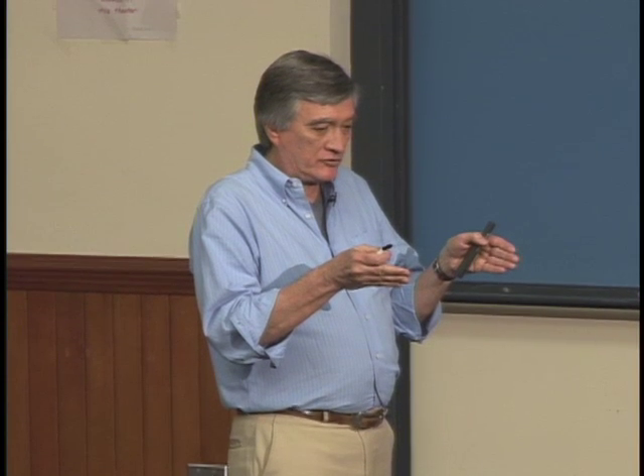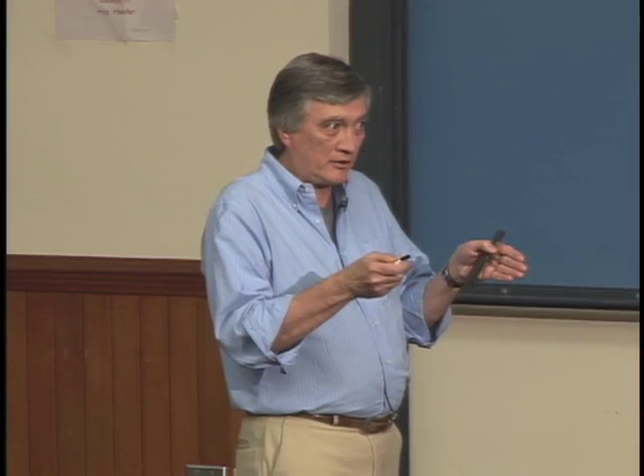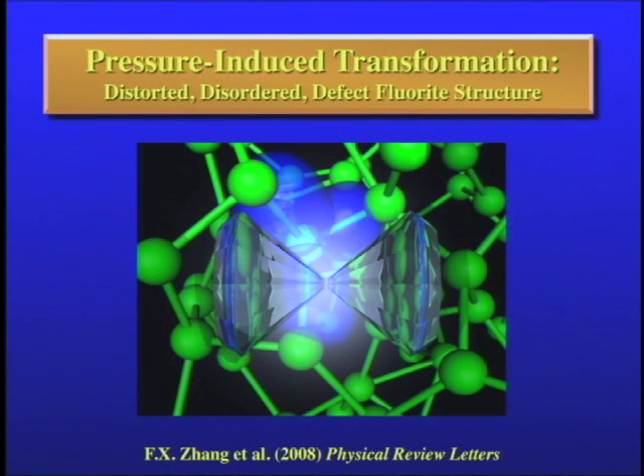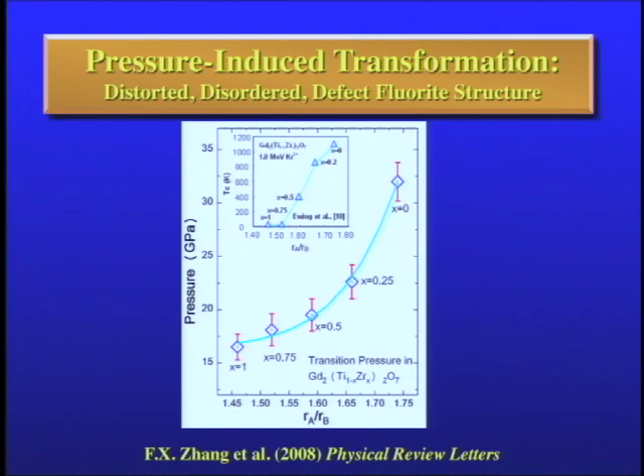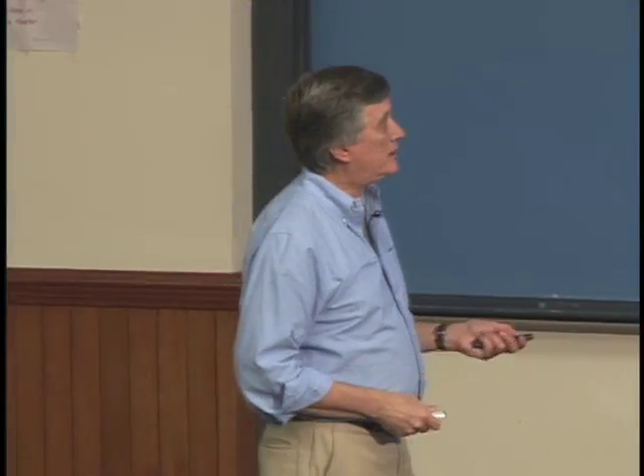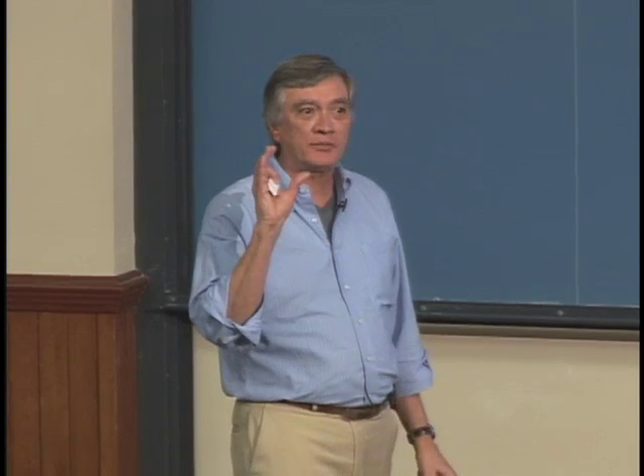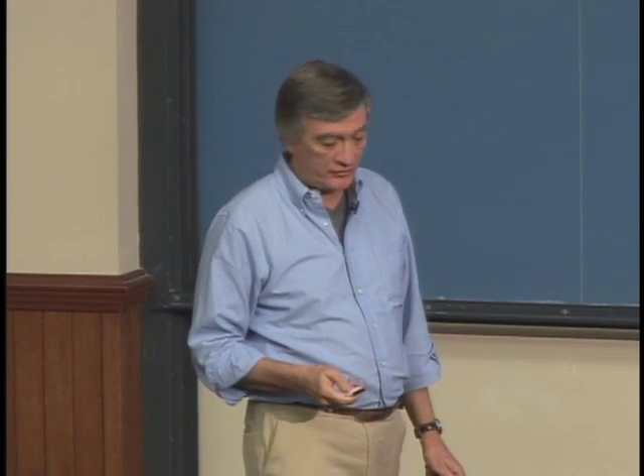If we think about radiation damage as a probe, what about pressure? And so with some trepidation, we entered the mineral physics world and began to do high pressure experiments on the pyrochlores. And the inset here shows the decrease in that critical temperature as a function of increasing zirconium content. Well, pyrochlore has a high pressure polymorph. It has several, which I would describe as distorted, disordered, and defective. Okay? The transition temperature to this high pressure polymorph as we add zirconium in a very analogous way drops with increasing zirconium content. And this is because the radiation damage is controlled by the energetics of the disordering, and in the same way, the pressure of this phase transition is controlled by the energetics of the disordering. So it's not a surprise that they're related.